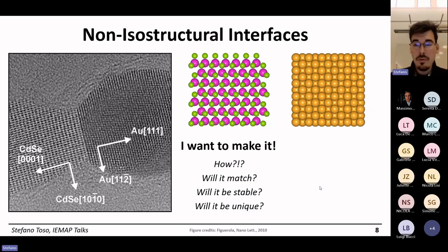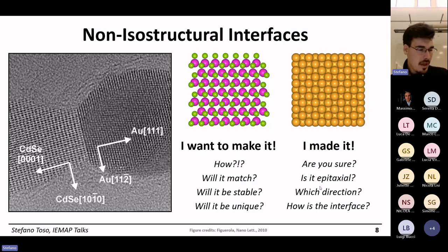And there are even more challenges, if you want, when you actually make the interface, because maybe you think that you have done a certain interface, but you have done another one. Or you think that your interface is epitaxial, but in reality, maybe you have a strong defectivity at the interface, or it's even amorphous. Maybe you didn't control properly the direction. This is less relevant if you are working in a thin film kind of configuration, but for us who work in colloidal nanocrystals, it's really difficult to decide where the two materials will attach to each other, right? It's not so trivial. And of course, you want to know a model of the interface to be able to characterize it and study its property, maybe simulate its properties.